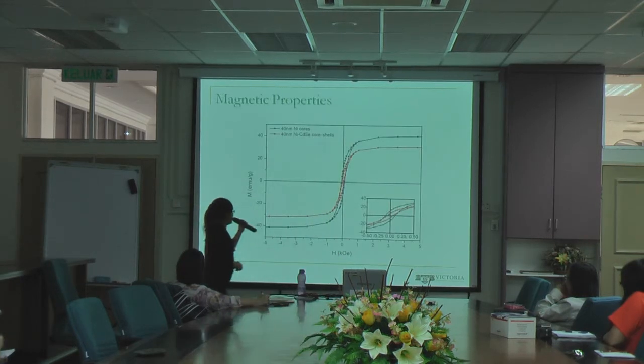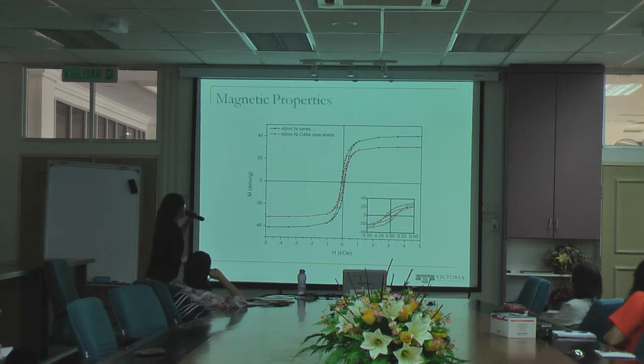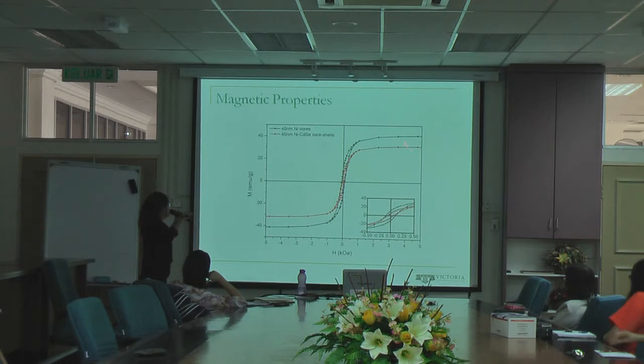So when we come to the magnetic properties, what we are really interested in is the region at the back here. This region is really a measure of the magnetic strength of the material. The black line is for the uncoated nickel, and the red line is for the coated nickel. So what we are seeing is that the magnetic strength decreases after coating with cadmium selenide.